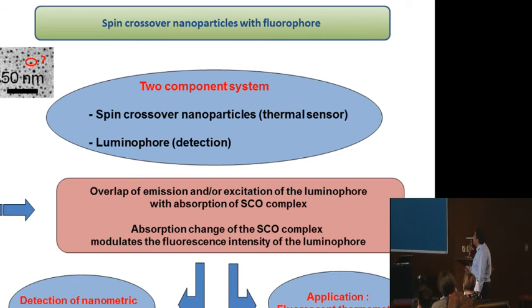So the idea was to know if it's possible to probe the spin crossover property of single particles. For this, we developed, as Azim said, the two-component systems, which consist of combining the spin crossover nanoparticles with a luminophore for the detection. Again, we need an overlap between the emission of the fluorophore and the absorption of the complex in one spin state. Like this, the absorption change of the complex should modulate the fluorescence intensity of the luminophore.